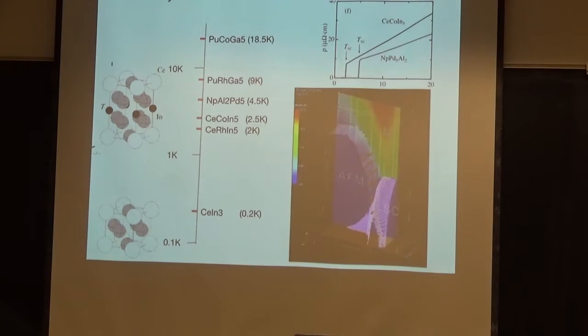And if you look at the normal state of these systems, they all show these nice linear resistivities coming down. If you didn't know, you'd say maybe that's a high temperature superconductor, and it is. It's just rescaled. And the reason the T_c goes up from cerium cobalt to plutonium is just that the characteristic scale of the plutonium 5f electrons is 10 times larger than the 4f cerium electrons. So if you look at the scaling that's gone on here, it's gone from 0.1, 0.2 Kelvin up to basically 20 Kelvin. Two orders of magnitude increase in T_c from the original material.